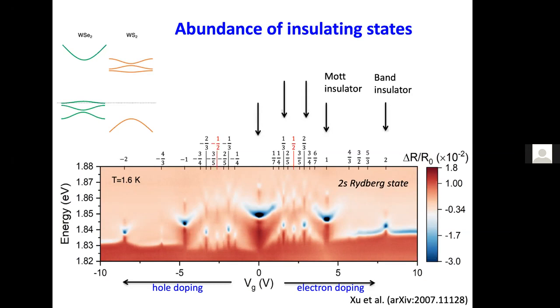So at these half-filling states that have the stripe order that you guys mapped in another data set, you discussed a little bit how on repeated thermal cooldowns the stripe order rearranged into new sets of domains, more or less freely, spontaneously. So that sort of indicates that the order is spontaneous and not really pinned to strain in the lattice or anything. Have you guys tried any techniques for biasing towards one stripe order, like trying to cool down with strong polarized light or anything like that?